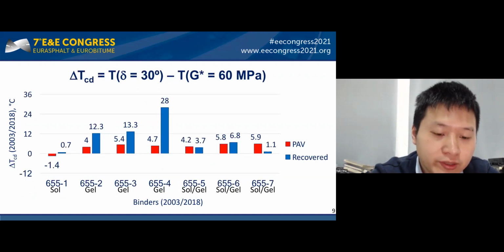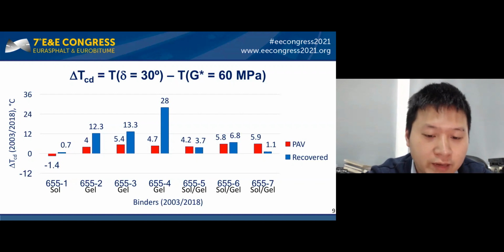So to capture not only the limit, but also the rheological type of the binder, we have introduced the delta TCD, where C stands for the limiting critical phase angle and the complex modulus G star temperatures, and D stands for DSR. We can see once again that there is a reasonable spread for the PAV residue, but the recovered binders are significantly more spread out. So this once again points to the inadequacy of the RTFO and PAV aging protocol.